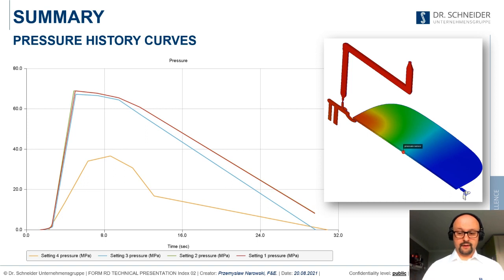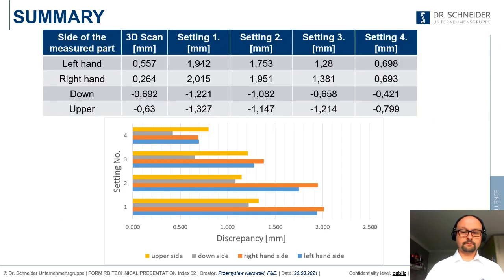Setting 3 was the simulation with this hot runner geometry, and here we can see a bit of a change. Yeah, the pressure is lower due to the pressure loss in the hot runner. But only the last curve, the orange one, which is our setting 4, the simulation with the data of the characterized machine, is completely different. The pressure is much smaller than it was at the beginning, and that resulted in more accurate, better displacement results after the annealing.